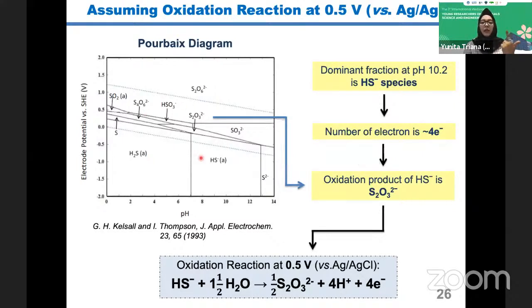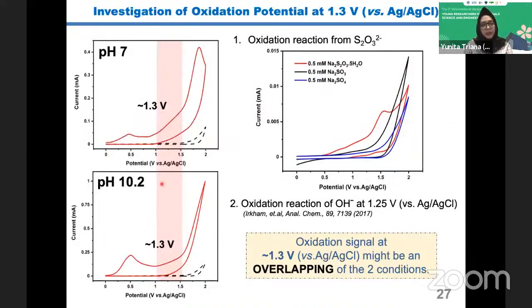And based on this Pourbaix diagram, at pH 10.2, you can see 10.2 here is the area of S2O3 2 minus. So my hypothesis is that the oxidation reaction at 0.5 volt is HS minus plus H2O becoming S2O3 2 minus plus 4H plus via 4 electrons. And how about pH 7 and pH 10? If you remember, I got 1.3 volt here, right?